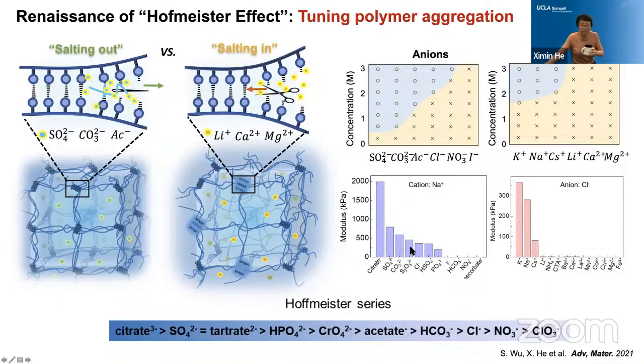So by choosing the ions from one end of this spectrum of the Hofmeister series, the ions can promote the aggregation between the polymer chains. Here in this model study, we utilize polyvinyl alcohol, which is rich in the OH group, the alcohol groups, so they can form a lot of hydrogen bonds between themselves. So these ions help remove the water molecules away from the polymer chain, so the chain-chain aggregation will induce a tightly bound polymer network.